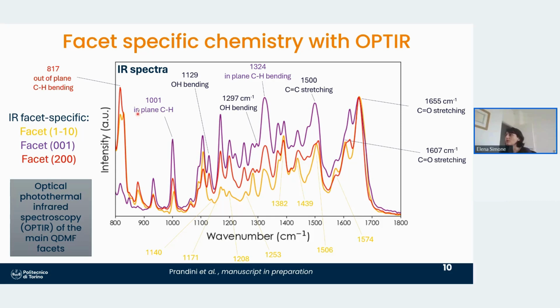And as you can see, those are all normalized data. They are averaged on different points of the same facets and of different crystals. And you can see that there are quite a lot of differences among the different facets. We're still analyzing this data, but we saw that the main differences are related to the CH bending modes, especially the out of plane and in plane ones.